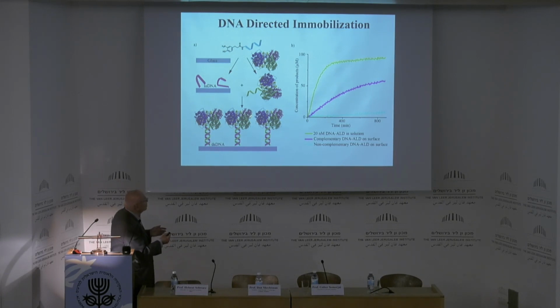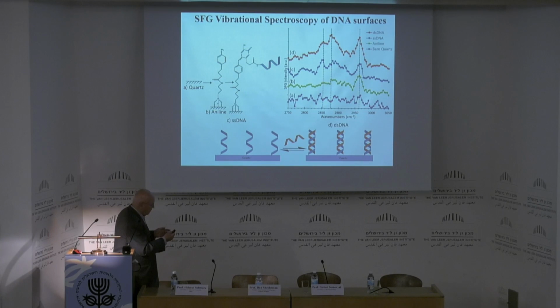Now, when you do this reaction in the water solution, you get this turnover rate measured by NADH formation, and you get 50% when it's anchored to the surface. And it stays on the surface without leaching for many, many turnovers. So it appears that we can heterogenize enzymes, and then this is the SFG spectrum, the vibrational spectrum of the single strand, the double strand DNA, and we are on the way to get the vibrational spectrum of the enzyme as well.